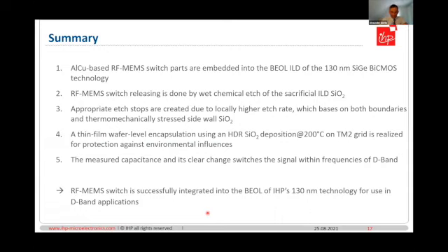So finally, I want to summarize my talk as follows. The aluminum copper-based RF-MEMS switch parts are embedded into the backend of line ILD of the 130 nanometer SiGe BiCMOS technology. The RF-MEMS switch releasing is done by a wet chemical etch of the sacrificial ILD silicon oxide. Appropriate etch stops are created due to locally higher etch rate, which is based on both boundaries and thermomechanically stressed silicon oxide. A thin film wafer level encapsulation using a high deposition rate silicon oxide deposition at 200 degrees C on top-metal grid is realized for protection against environmental influences. And finally, the measured capacitance and its clear change switches the signal within frequencies of D-band.